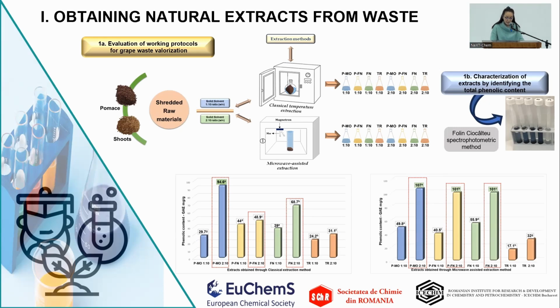After the extracts were obtained, they have been characterized by identifying their total phenolic content using the spectrophotometry method with Folin-Ciocâlteu. From the results, it can be observed that the total phenolic content of the samples varies depending on the raw materials used, the ratio applied, and also the extraction method. The best results were obtained in the case of the extracts obtained in 2:10 ratio. And it can be observed that these results were obtained with the modern extraction method. So these extracts were selected for the further experiments.